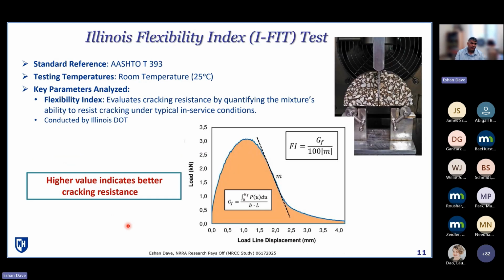Illinois Flexibility Index Test or IFIT, again, there's AASHTO standard for it. Similar in concept. So here the main advantage is it's truly a fracture mechanics driven test with a notch, unlike CT index where you're just looking at overall breaking susceptibility of your mixture. And typically, once again, you want a higher value to get better cracking resistance. It's once again looking at that area under your load displacement curve that represents the total work it takes to break the specimen, but also it pays attention to how quickly the crack travels through the specimen, what's your crack velocity, and that's done by looking at the slope on the post-peak side to get your composite index called flexibility index. Now, as with CT index, all of this testing was done at 25 degrees Celsius in this particular project.